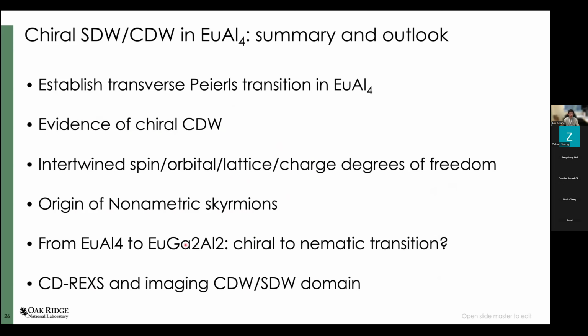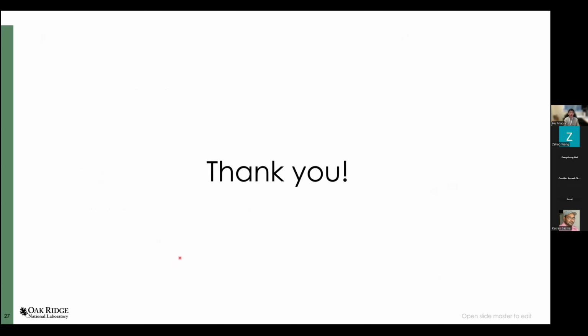Another interesting observation for this material is that on the europium aluminum side, the CDW is C4. But if you dope like 50% gallium, then the CDW is C2. So we're interested in how the CDW changes from four-fold symmetric to two-fold symmetric. And also, we are actively pursuing directly imaging the CDW and the SDW domains using resonant elastic X-ray scattering. Then we might be able to comment more on the nature of chirality flipping and the chiral spin density wave. And with that, I think I can stop here and I'm happy to take your questions.